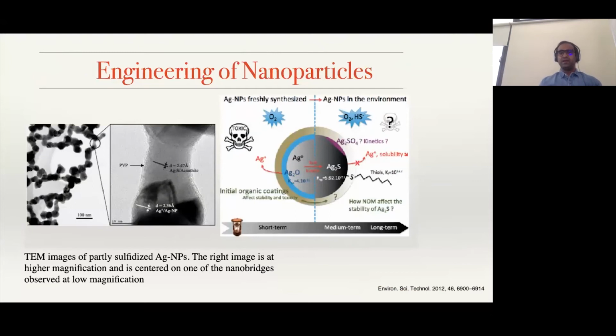Now, this is a very interesting example, which I think I should talk about a little bit. Over here, we are showing a transmission electron microscopy image of silver nanoparticles. And this silver nanoparticle is not really a silver nanoparticle when it goes inside the body. The reason is that if you look at the surface of the silver nanoparticles, silver is known to dissolve. So as soon as this particle comes in contact with a fluid, it will release a silver ion. Now this silver ion is an unstable material. It will try to immediately complex with something. If there is a presence of chlorine, we know that silver combines with chlorine and creates a silver chloro complex. But if there is even the presence of sulfur, the silver can also combine with sulfur and form silver sulfide. As soon as a silver ion comes from the surface, it will form a complex and then reprecipitate on the surface itself.